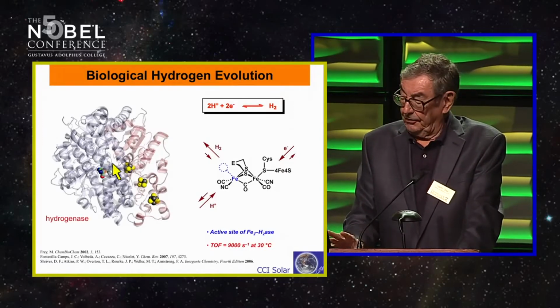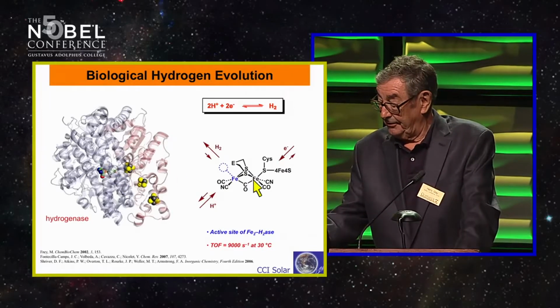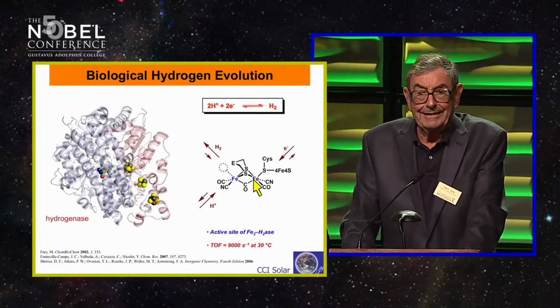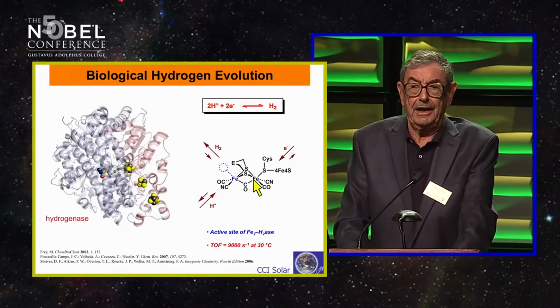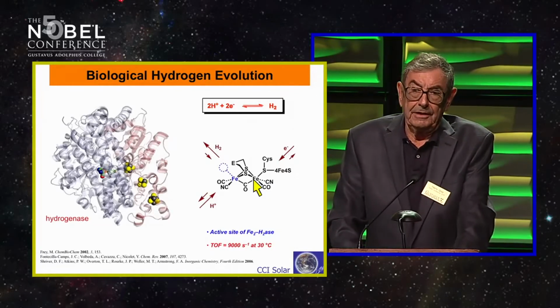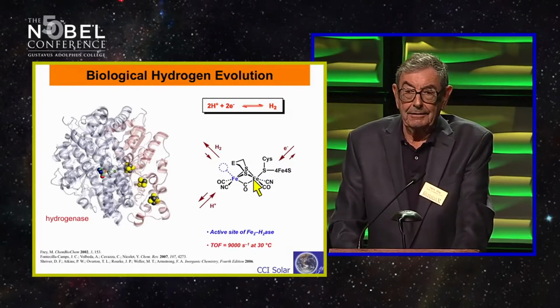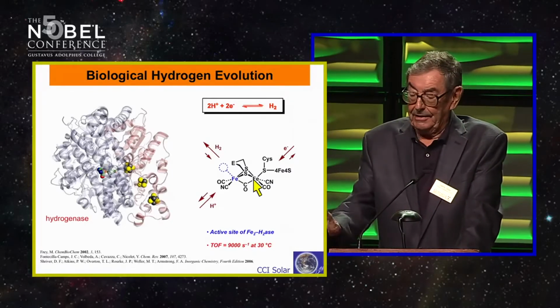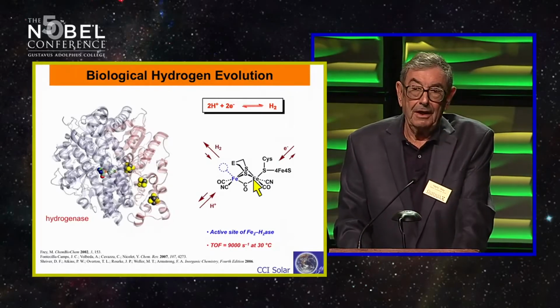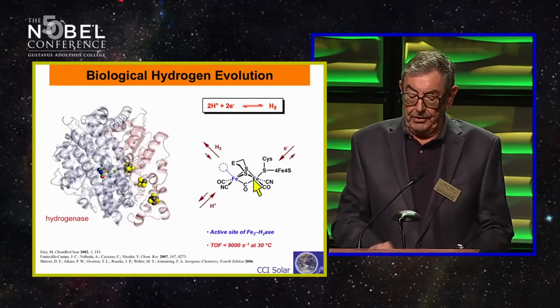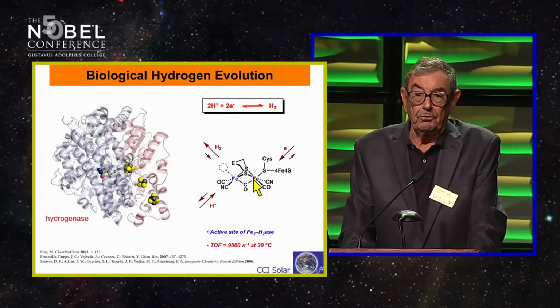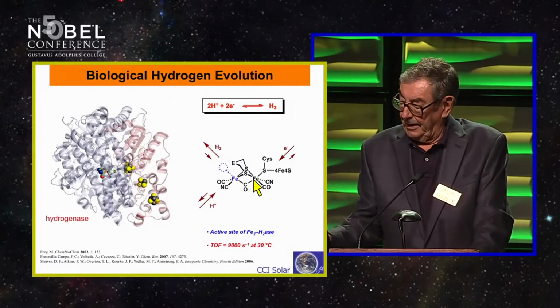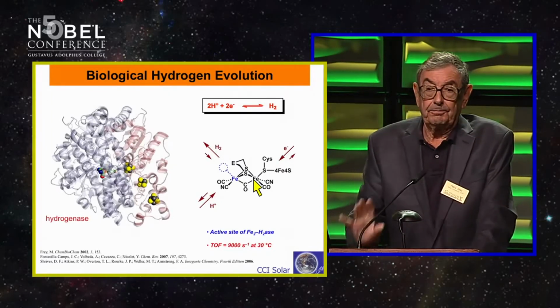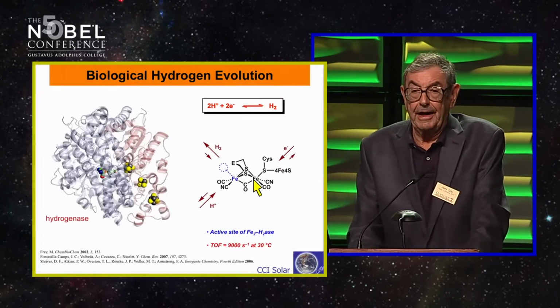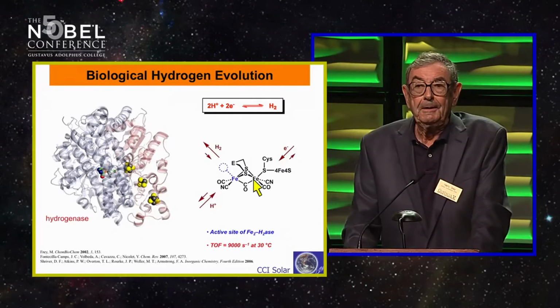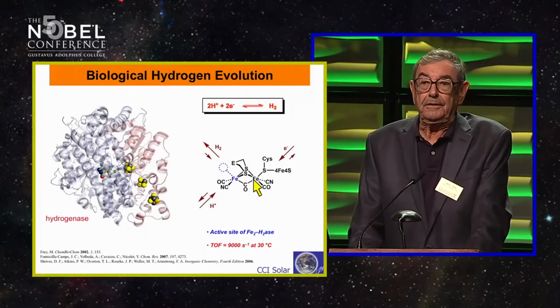For a while, we thought we could just take the active sites out. The active sites are these nice inorganic complexes. We could take them out and use them on our silicon photocathodes. But one lesson we've learned in 35 years of working in bioinorganic chemistry is that when you take the active sites out of a protein, they don't work anymore. They need the protein interactions inside the protein cavities to work properly. A good rule of thumb is that if you take a redox center out of a protein, its potential, the potential at which you could evolve hydrogen, changes by about 1 volt. And that's just too much. We can't reach that with solar energy.